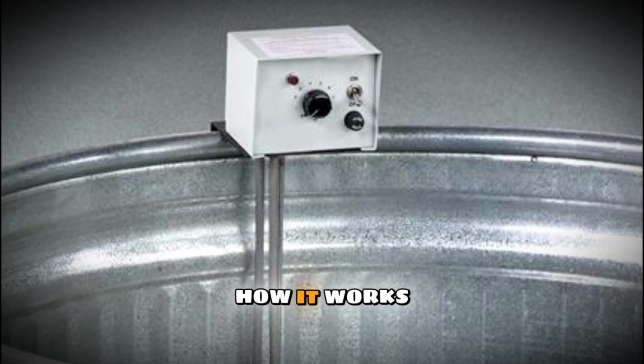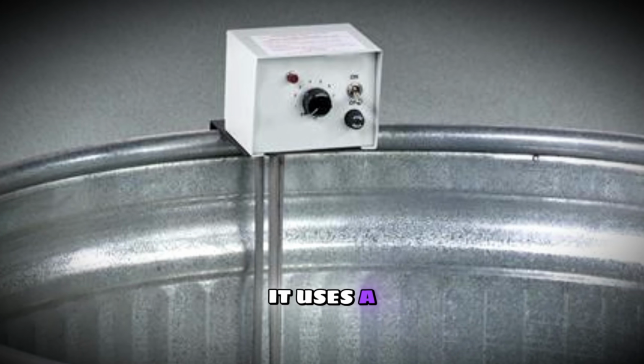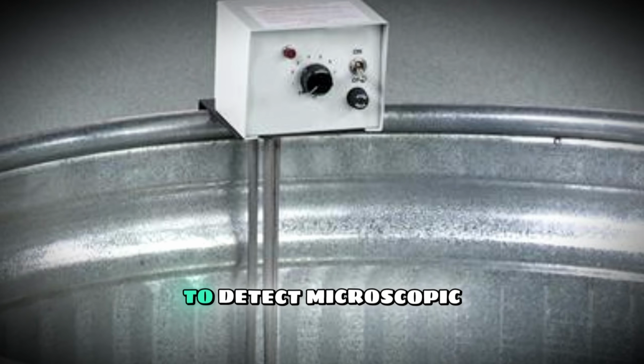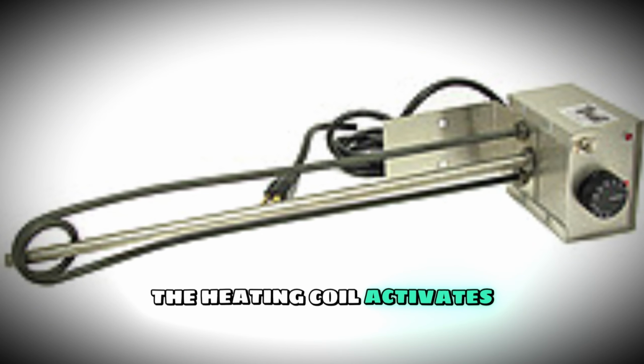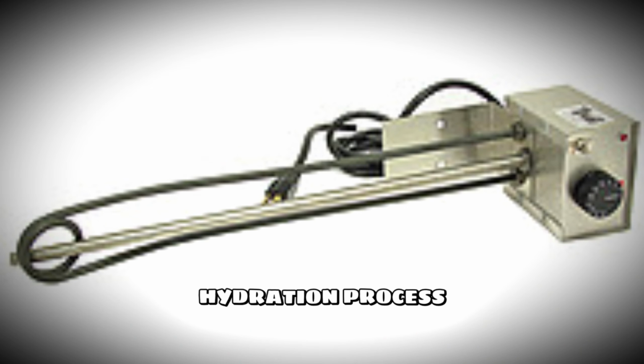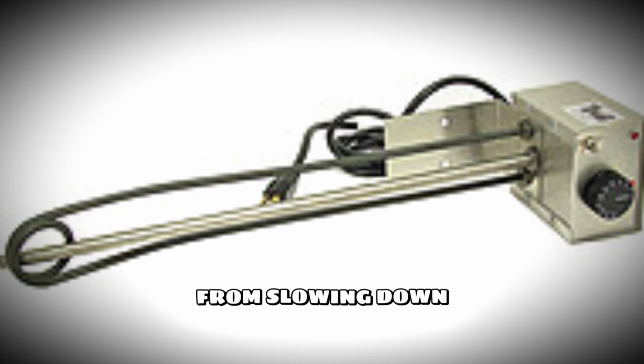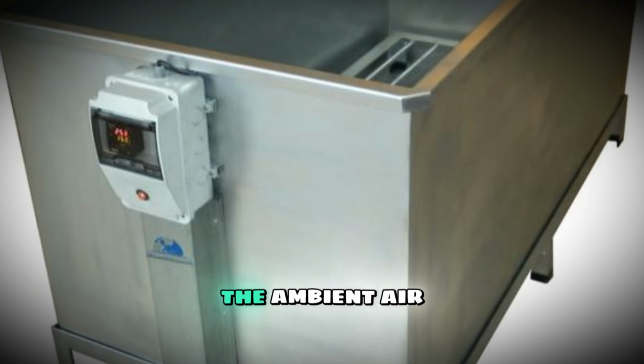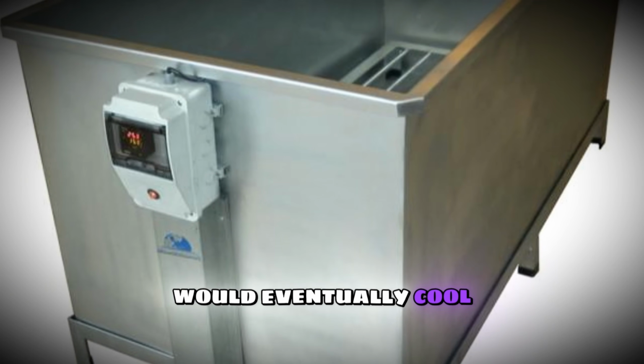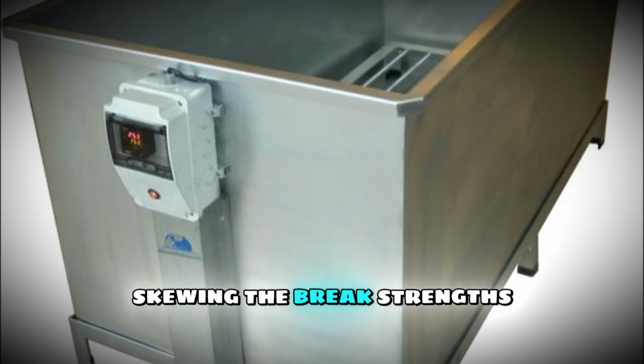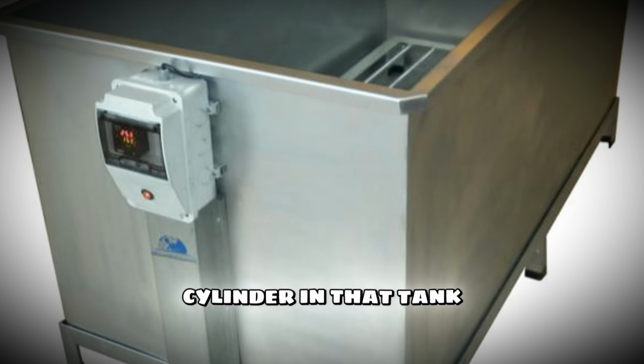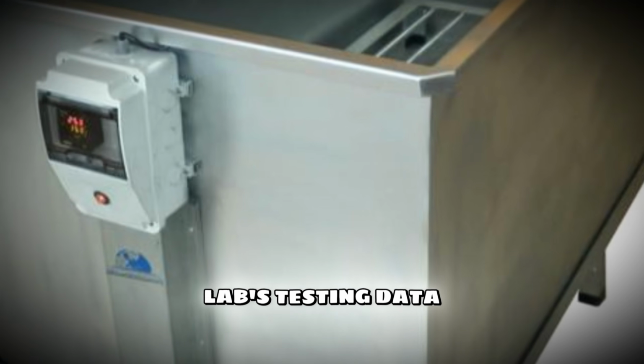How it works: submerged directly into the tank, it uses a sensitive thermostat to detect microscopic drops in water temperature. When the lab gets cold at night, the heating coil activates, gently warming the water to prevent the hydration process inside the submerged cylinders from slowing down. Why you need it: without a reliable tank heater, the ambient air conditioning of a laboratory would eventually cool the water tank down, skewing the break strengths of every single cylinder in that tank and invalidating the lab's testing data.